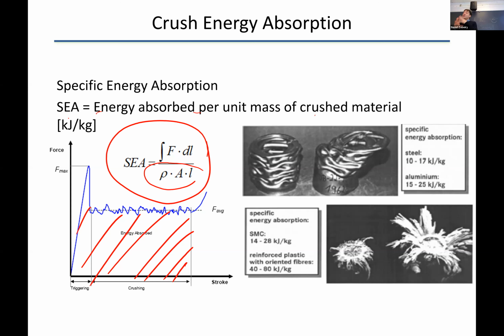So first of all, if you're comparing aluminum and steel with composites, you're dividing it by mass, so the density of composite is lower, so it's to their advantage. But kilograms to kilograms, which one is better? Because for flying, it's better to have lighter components that absorb energy more. So if you have metallic components like steel, and we're talking about circular, it can absorb 10 to 17 kilojoules per kilogram. And again, steel is quite heavy. If you replace it with aluminum, you will increase it to 15 to 25 kilojoules per kilogram.